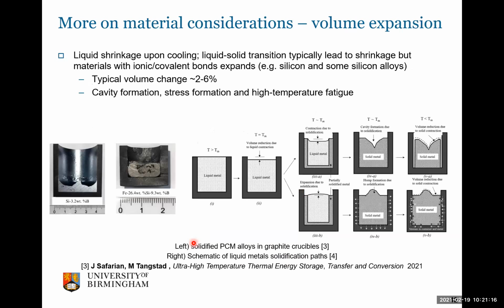Another aspect I think is important to consider, and that is not necessarily always a priority when high temperature thermal storage systems are developed, is the volumetric expansion of PCMs. Let's say in this case metallic PCMs at high temperature. Typically, depending on the metal or alloy considered, we have volume changes that might be between 2% to 6%, which might ultimately lead to cavity formation during the solidification and melting process, and also to stresses in the containment, as well as potentially high temperature fatigue.